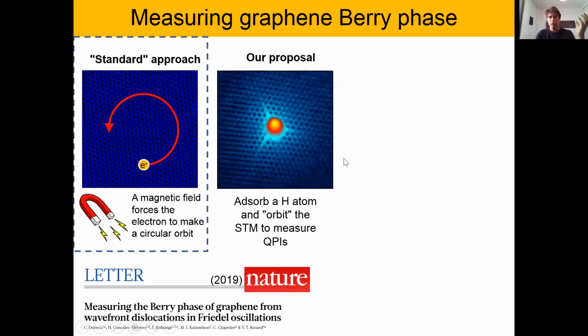We have graphene, and what we do is put a single scatterer here, a point defect. In our case, this is a hydrogen atom. So now electrons come from all directions and they scatter against this hydrogen atom and get reflected on it. So instead of circulating the electron, what we do is circulate our tip. We go with our tunneling tip, and we measure the scattering events along all directions. And this is equivalent to making the electron circulate.